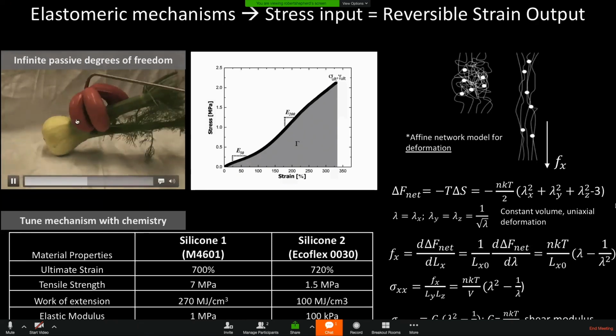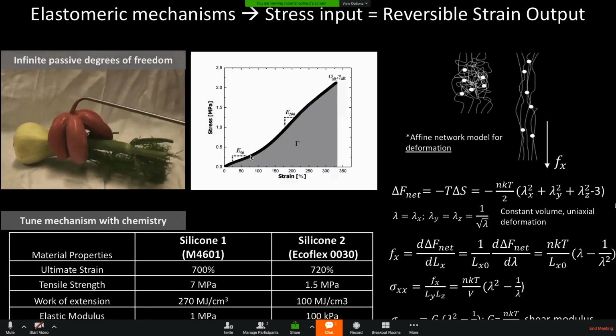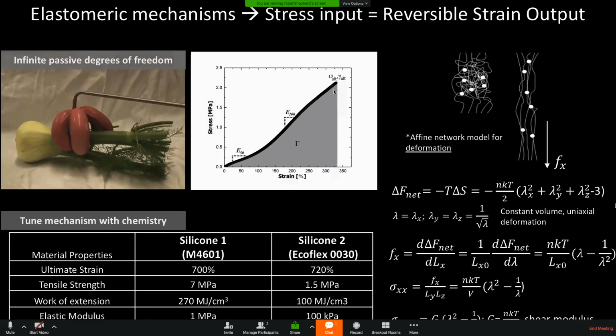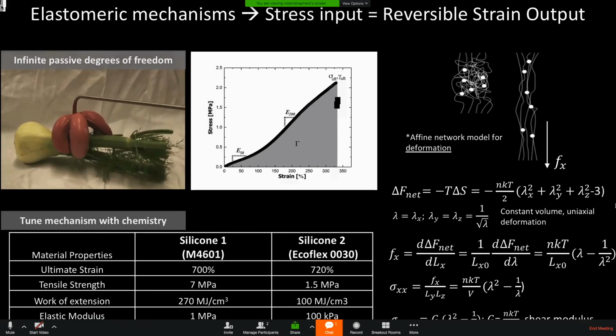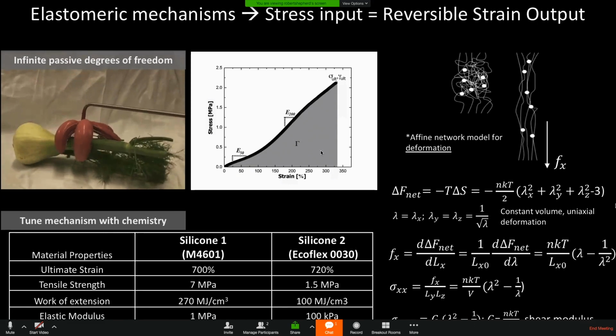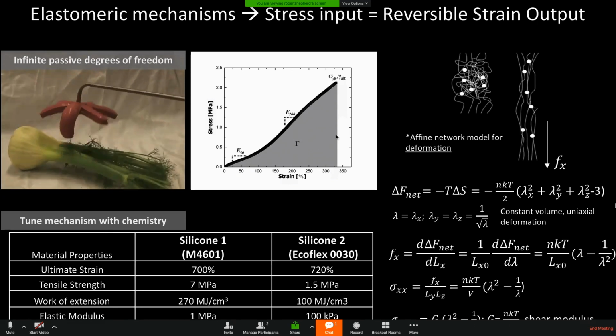These balloons are deforming based on the stress strain curve, so the slope of this curve, and the integral of this curve before the rubber ruptures is its toughness, and the amount of energy that these materials can absorb are very large. I'm calling it work of extension here, because if you don't rupture it and you just come up the slope and then come back down, that's called the work of extension. But the work of extension at failure can be megajoules per cubic centimeter, which is very large.